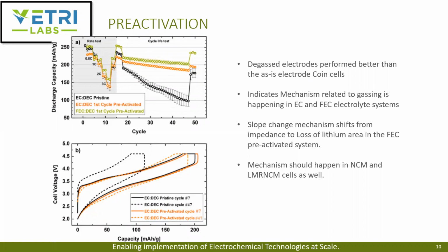Again, they did this both in the NCM and the lithium manganese-rich NCM cells as well. It all comes back to the mechanism of gassing, and then the oxygen that is produced chemically reacting, not electrochemically, but chemically reacting with the electrolyte systems.